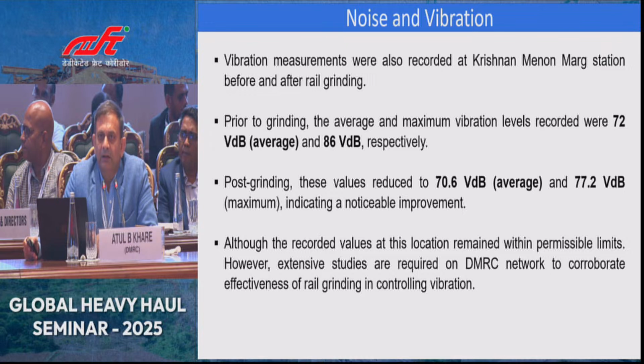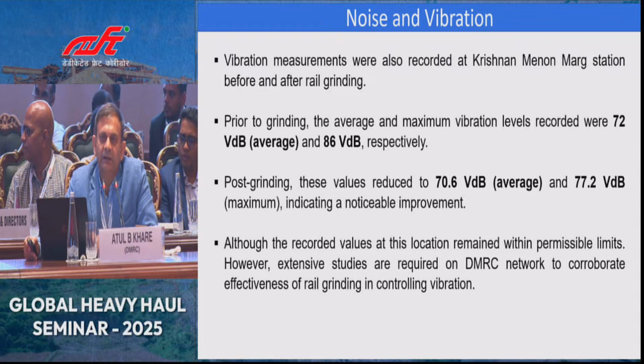Again, at one of the locations, we have also recorded the ground vibration level at the pre-grinding stage and post-grinding. With effective grinding, the vibration level has reduced, which was 72 VdB average and 86 VdB maximum, to 70.6 and 77.2 VdB. This is specifically at the location where no vibration mitigation measures have been taken.